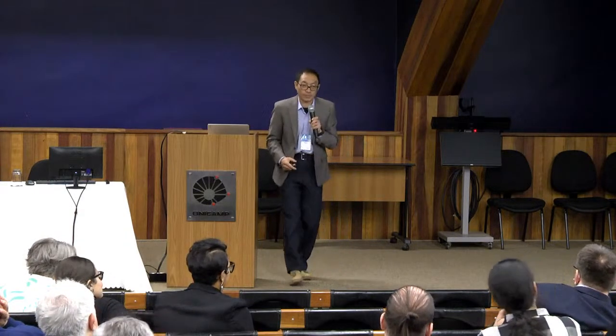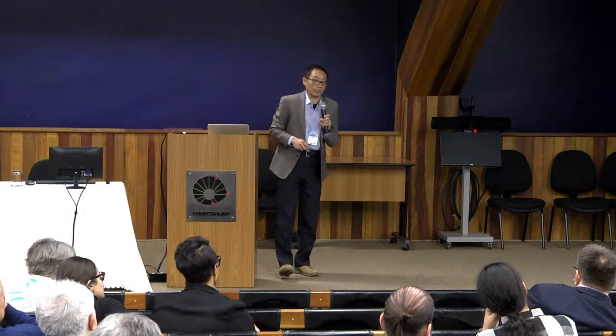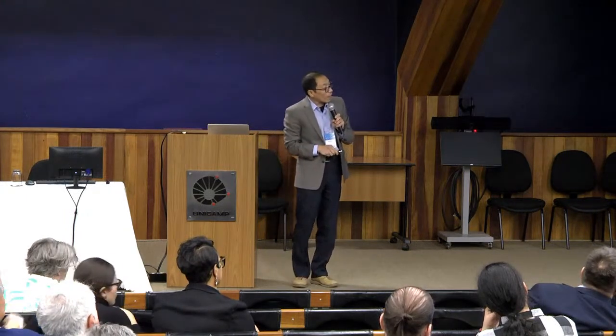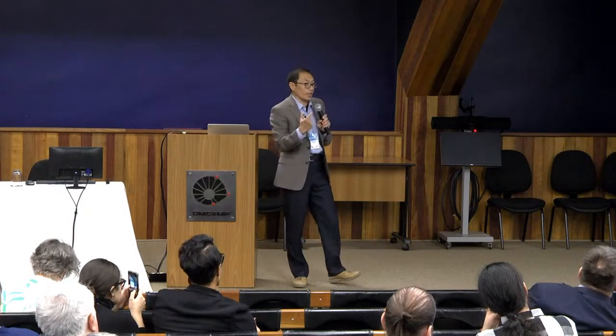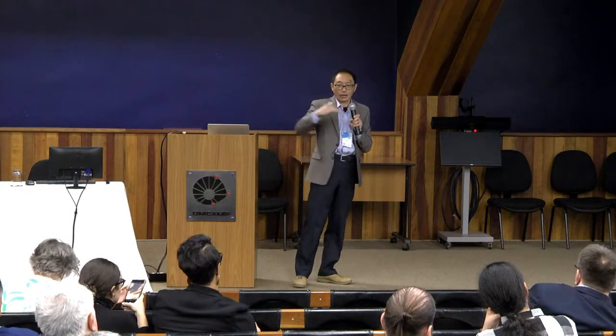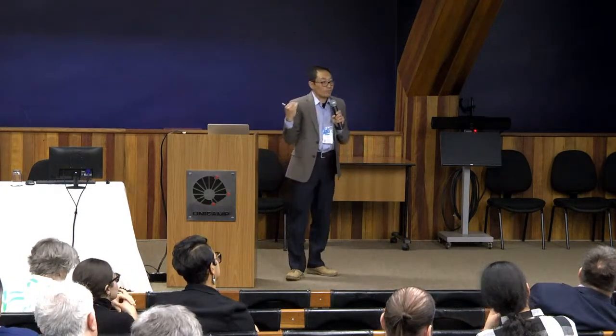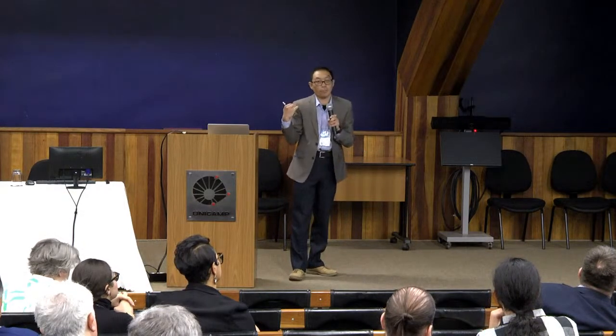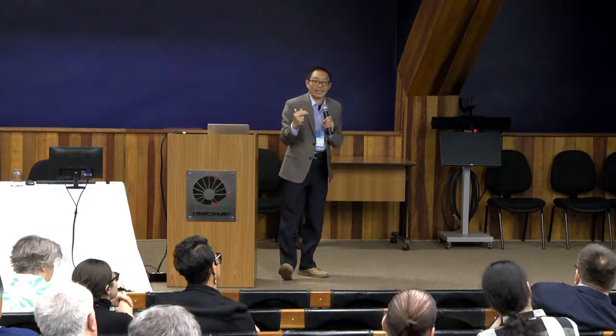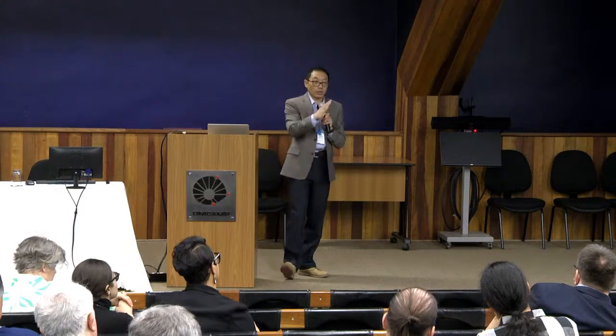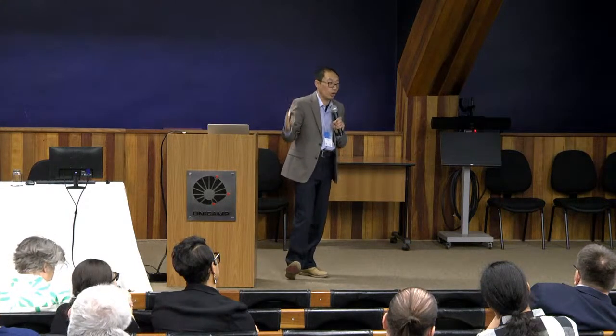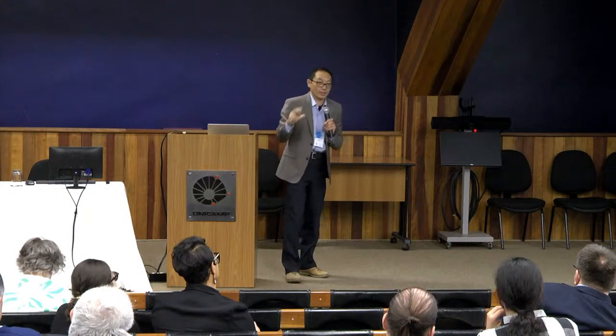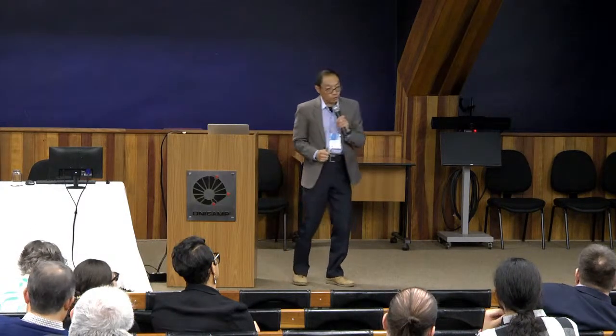And then what you will see is after hundreds of cycles, this is a material from Samsung, directly an industry standard lithium-rich compound. So when we cycle over 500 cycles, we will see the feature is showing up, disappear for hundreds of cycles without much of an issue. So we estimated the reversibility after 500 cycles, about 80% still retained. By the way, industry standard is after 1,000 cycles, the total capacity of your battery should not drop below 80%. So that's an industry commercialized cell standard. This is not there, definitely.